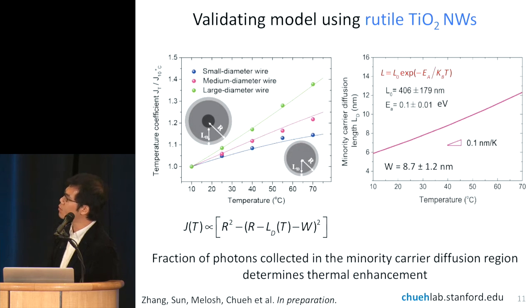And this is a plot showing you how temperature is activating the minority carrier diffusion length from about 6 nanometers at 10 degrees Celsius to 12 nanometers at 70 degrees Celsius. And we're also able to extract a space charge layer width of 9 nanometers, which is very comparable to what's expected for this substitution level in titania. And we're also able to back out an activation energy of 0.1 electron volt, which is consistent with the type of electron trapping that you see in titania.